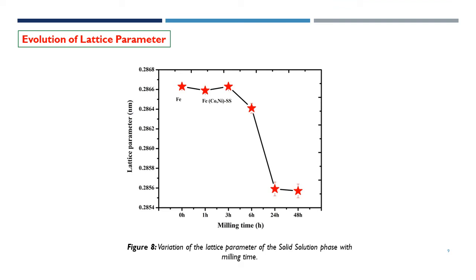Figure 8 shows the change in the lattice parameter of the milled Fe50Co40Ni10 alloy powders with milling time. The change in the lattice parameter indicates that the milling process has produced an atomic disorder. Before milling, the lattice parameter of the iron BCC structure was 0.2866 nanometers. After 6 hours of milling, a rapid decrease in the lattice parameter is observed. With prolonged milling time, the lattice parameter continues to decrease, reaching a minimum value of 0.2855 nanometers at 48 hours of milling.